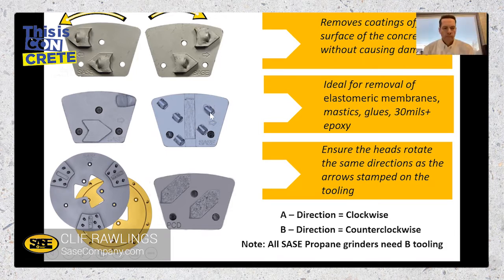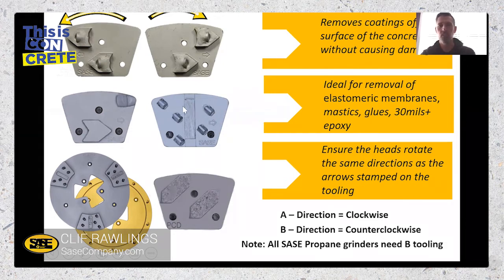Okay. And then you get to the less aggressive. This is, remember, the 1/8 cut PCDs spread out, and then we have a wear bar in the middle to again keep them from cutting too aggressively. What's nice about this one is if you've got a thinner to medium coating, you can still cut it off very efficiently, but without hurting your substrate below too aggressively by having this wear bar on it. And you can follow this up typically with, say, a 40 grit metal bond. Whereas these other two, especially this one, are going to take at least a 25 grit metal bond to remove the deep gouges that these leave behind.